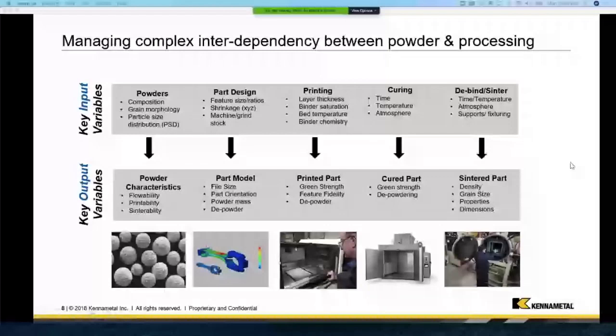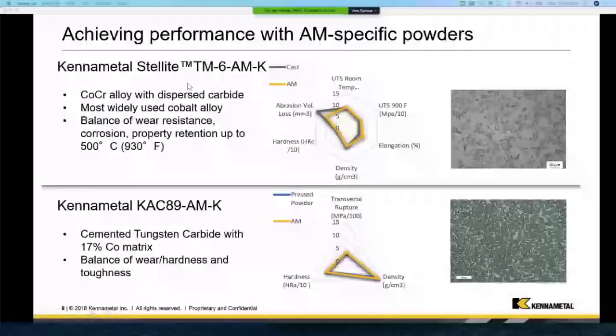When we look at what we're achieving, these are two of the Kennametal materials that we have refined and customized for 3D printing in the binder jet technology. They are Stellite 6 AMK, which is our additive specific Stellite 6. Stellite 6 is a cobalt chrome alloy that has dispersed carbides that makes it a very high wear cobalt alloy. It's one of the most widely used cobalt alloys, particularly in wear applications. It brings a good balance of wear resistance, corrosion resistance, and property retention up to about 500 C.